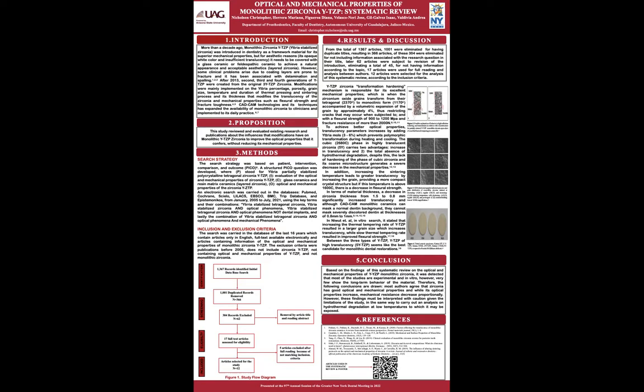And for the conclusion, we stated that most authors agreed that monolithic Y-TZP stabilized tetragonal zirconia has great optical and mechanical properties, but as we try to improve those optical properties for aesthetic reasons, there will be a proportional decrease in the mechanical side. I also invite my colleagues to do an analysis on the low-temperature hydrothermal degradation to which the material can be exposed, to interpret these results with caution, and to learn more about this material, to hopefully use monolithic zirconia restorations in aesthetic zones in the future.